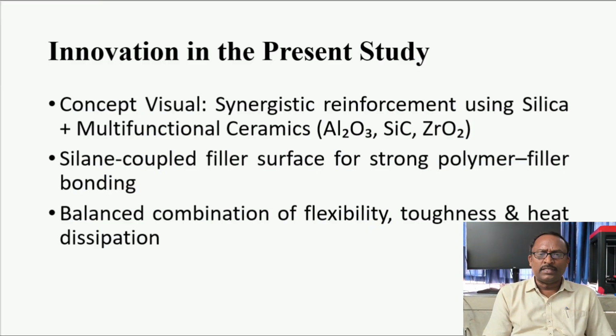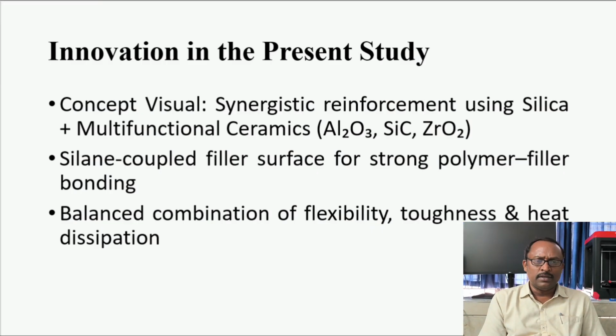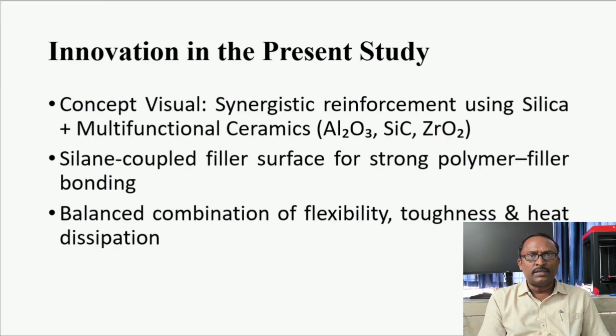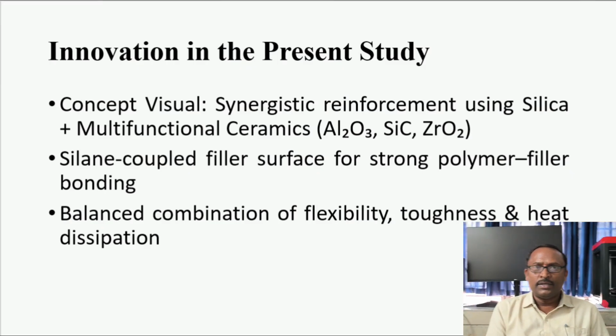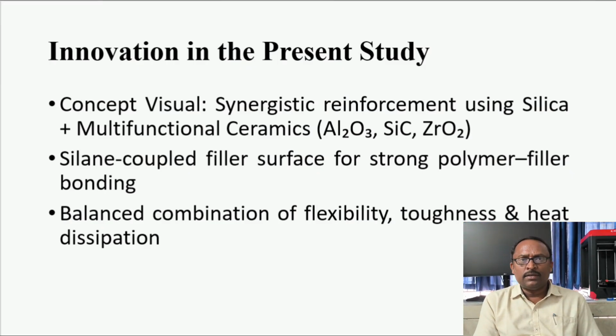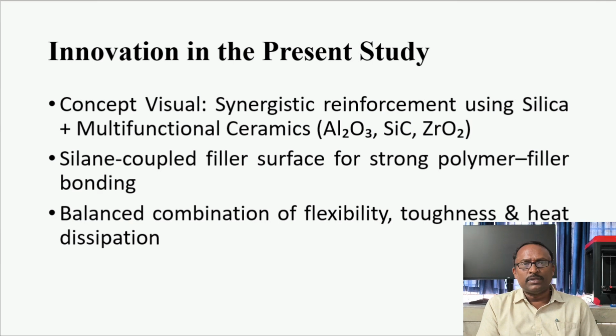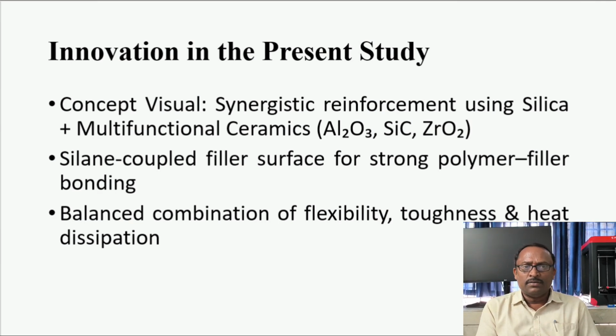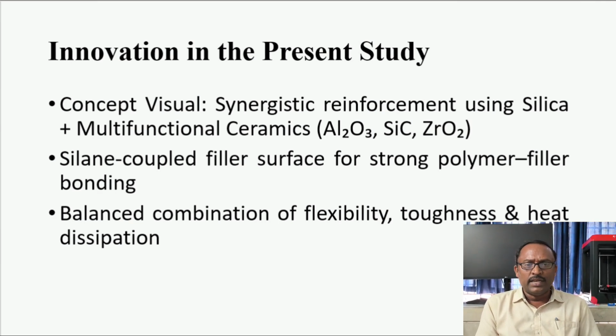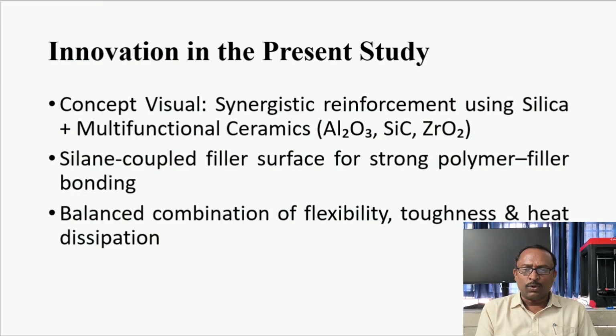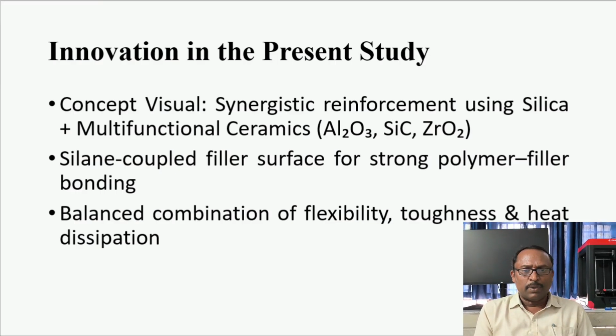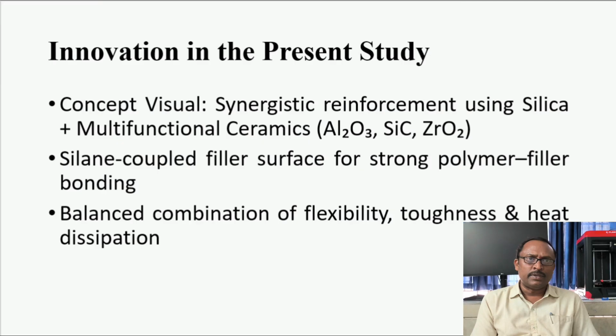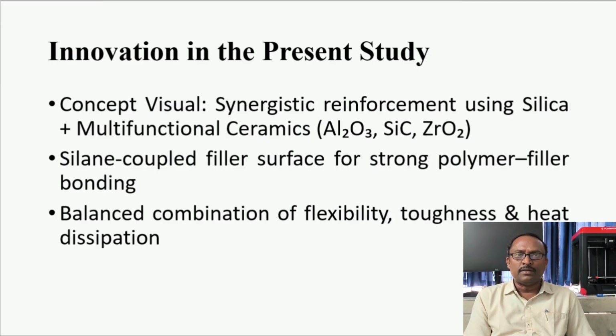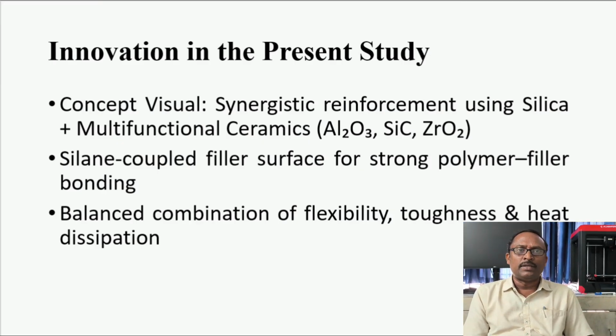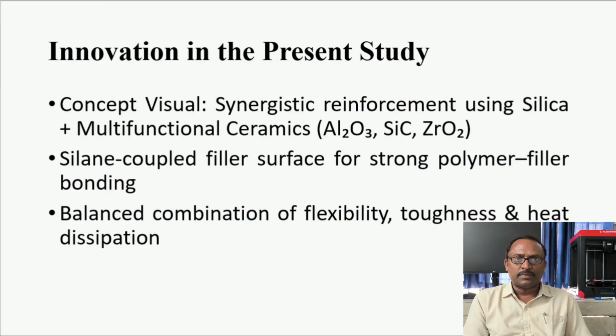Concept visual is a synergistic reinforcement using silica plus multifunctional ceramics, that is Al2O3, silicon carbide, and zirconium dioxide. These ceramic fillers are used in addition to the fused silica. You can improve the properties. Silane coupled fillers are used for strong polymer-filler bonding, a balanced combination of flexibility, toughness, and heat dissipation. These are very required and challenging for the tire material, where we need to balance all these properties.